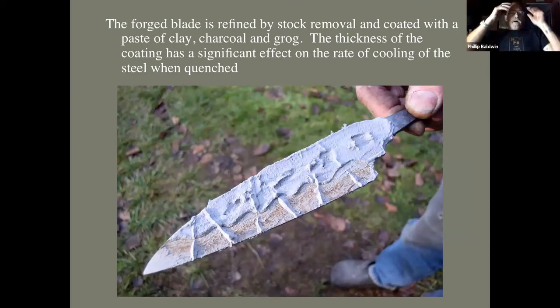Okay, I went for a Japanese style heat treatment on this, and that's with using the clay. This is something I've done since the very beginning. The mixture of clay that I use is from Yoshindo Yoshihara's book. It's about equal parts by volume of fire clay, a very fine grog, which is like a sand, and ground charcoal. This tends to stay on the blade, and you grind it up and slosh it on.